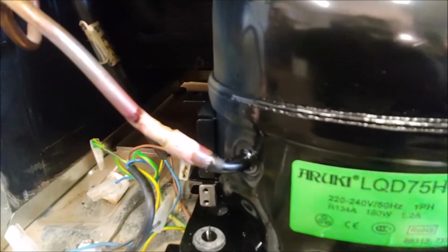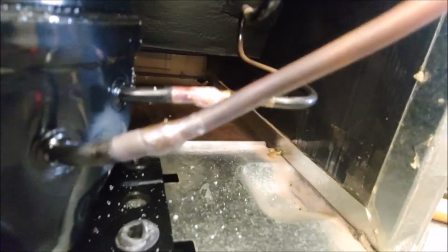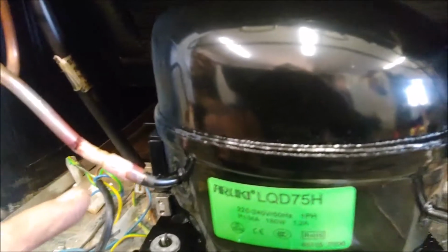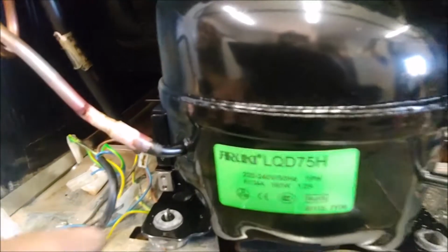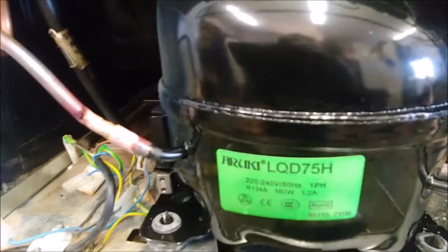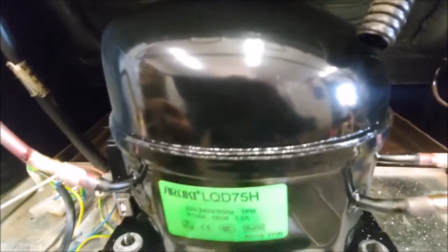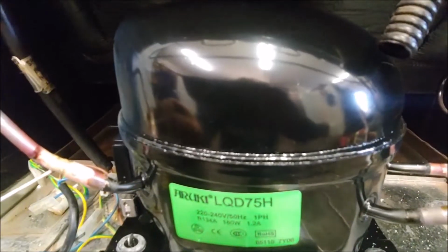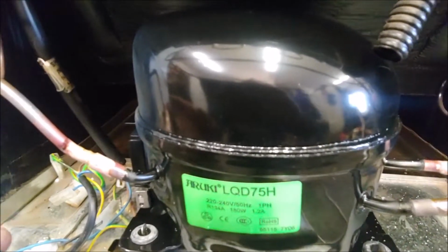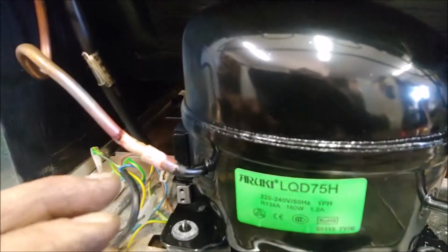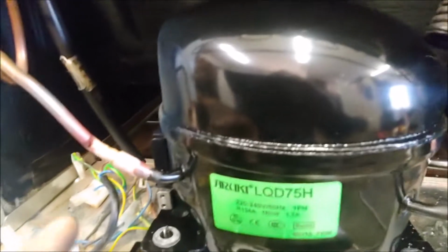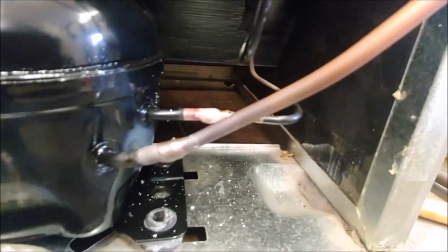Okay, I've done the welds here. That one there, silver solder. The one at the back, silver solder. This was just copper to copper and copper to copper here. On these welds that had the fridge braze on it, when I was welding it and I put the flux powder onto the fridge braze, it was still in a solid state. The minute the flux touched it, it became a liquid, and I mixed it with the silver solder and it made very nice joints there.